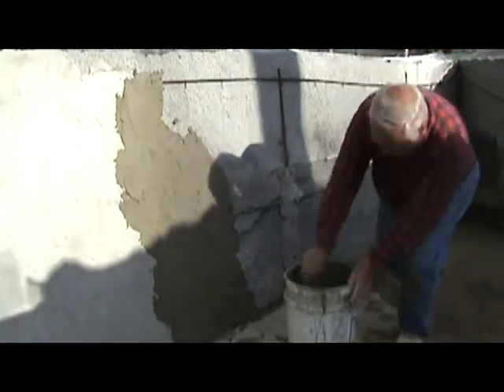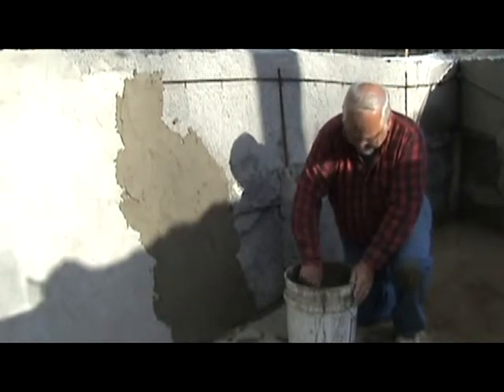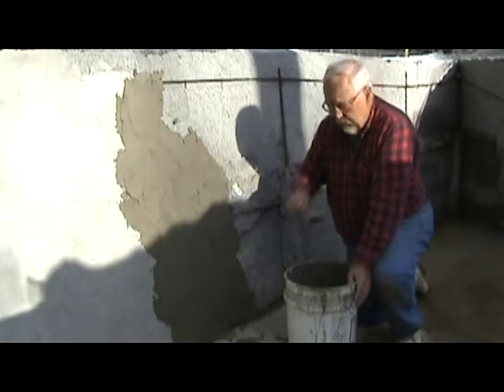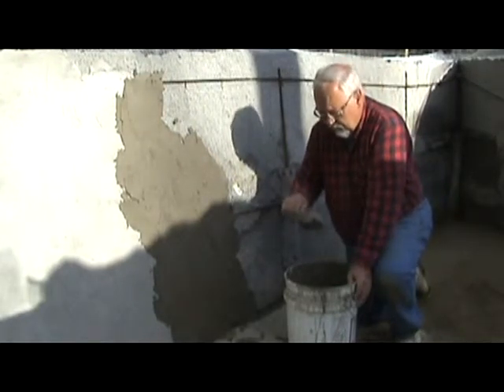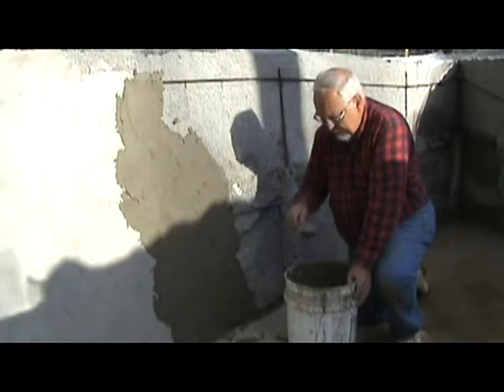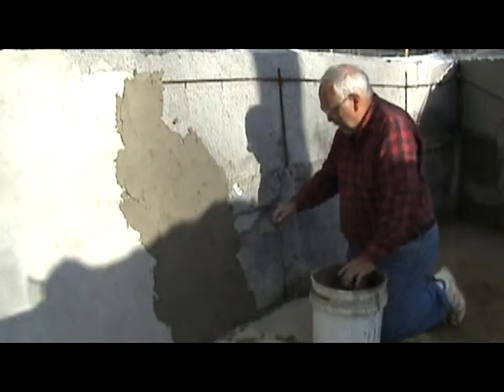This is the covering that goes on the walls. The mix is three parts sand, one part masonry cement, with a large handful of half-inch polypropylene fiber added to it. The liquid is three parts water and one part acrylic polymer.